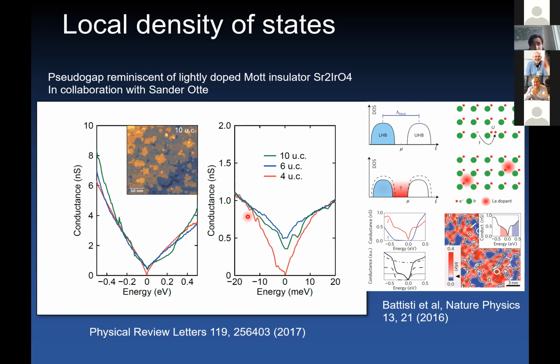And so through this effort, we were able to measure the local density of states of our thin films as a function of thickness. And so the result is shown here. What is important to see here is that we systematically observe, as a function of thickness, a reduction in the density of states around the Fermi energy, with a particular V shape of the density of states. So this type of behavior is reminiscent of a pseudogap, as observed in most lightly doped Mott insulators. In the strontium iridate 214 itself, this phenomenon is observed.